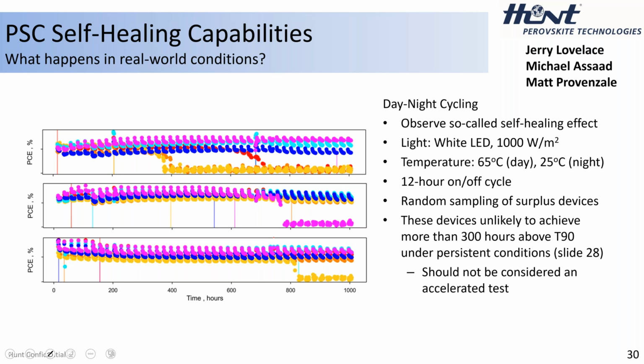And so kind of take a step back from that and make it more realistic. We can see that if you give the chance to rest overnight without heat, without light, as would be occurring in nature, the perovskite cell, this indicates, is vastly more durable than we're actually giving it credit for. Not going to carve that in stone. I don't have a piece of granite in front of me chiseling away, but it does indicate this may be a self-healing mechanism that really extends the lifetime of the device.